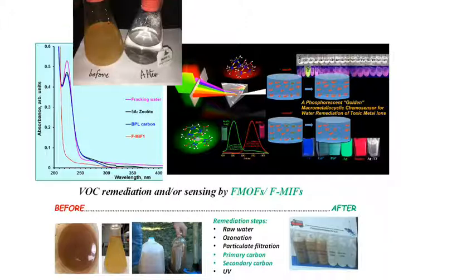Since our material is super hydrophobic, my students actually had the smart idea of making basically a tea bag out of this porous material. So we started from the fracking produced water. Produced water is what remains after the fracking fluid goes down and the site gets the natural gas. The natural gas is taken away and packed. There are still enough traces of gasoline and fracking fluid in the water. They skim off the surface, but there are a lot of surfactants that mix with the water. So even the produced water is supposed to be purified.